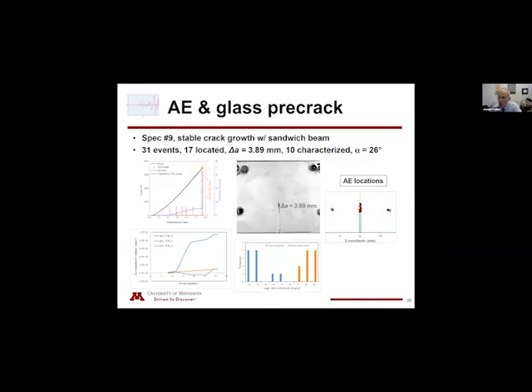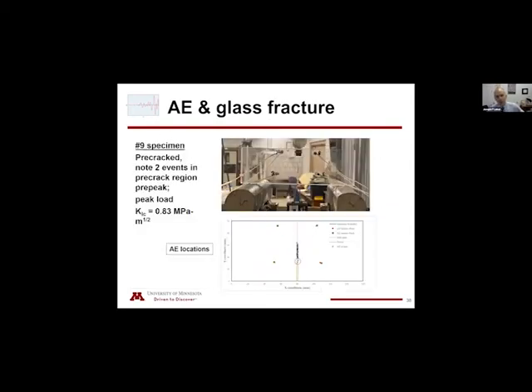If we look locally, again, we have mixed mode locally. Globally, these little cracks are opening with little displacement in the Y and Z directions. Finally, we were successful now with that pre-crack using conventional types of fracture test methods.